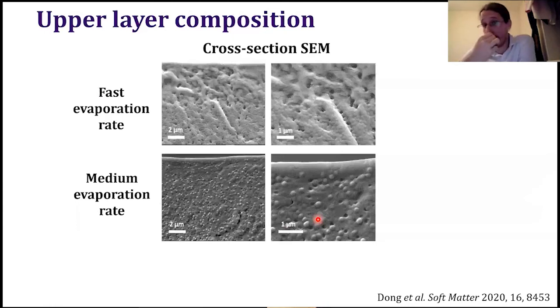And we also had a look at the cross-section in SEM as well. This is more or less the same. It's just corroborating what we saw using infrared spectroscopy, that for fast evaporation rate, we are here looking at the cross-section from the side of the coating. This layer of small particles, which you cannot really see because they are coalesced, is thicker than here, where you can see some medium particles are also going to the top. So that means that for fast evaporation rate, that top layer has more small particles, but we still see the stratification. We still have all these small particles at the top here and here. So it still seems it is making it a more reliable process than if we were using non-polydispersed blends.